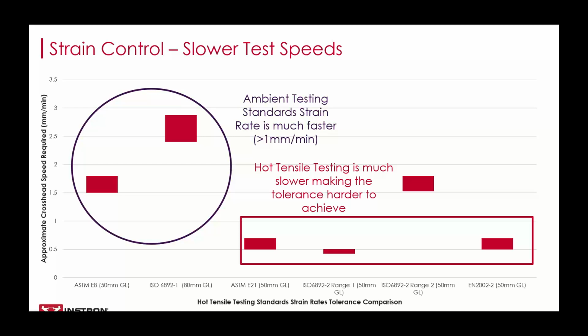This is what really drives the need for closed loop strain control in high temperature testing. Because of course, remember, it's not just that you need to find the right crosshead speed for your target strain rate, you also need to ensure that it's appropriate for the stiffness of the specimen, which can change from alloy to alloy, making it very difficult to identify the correct speed.